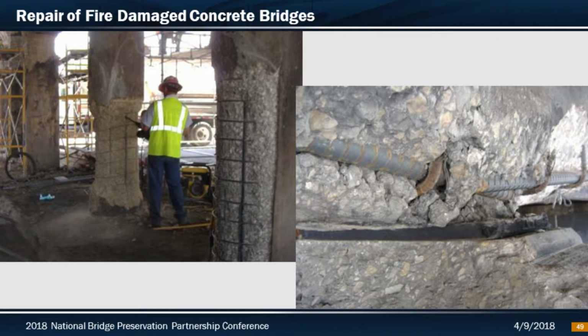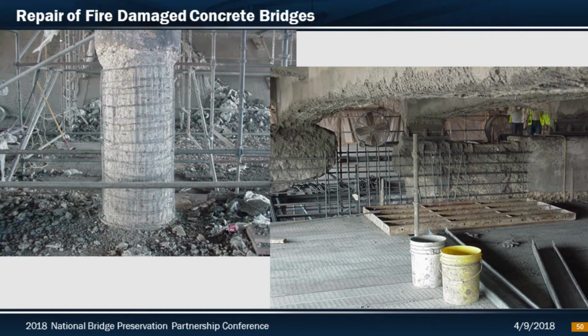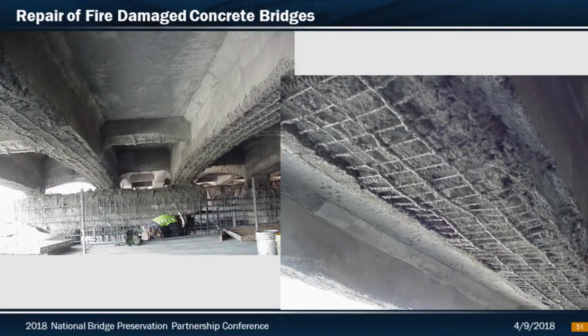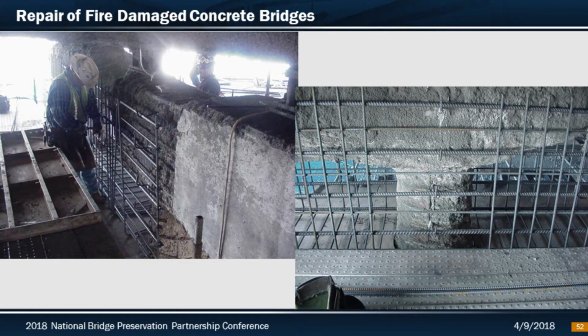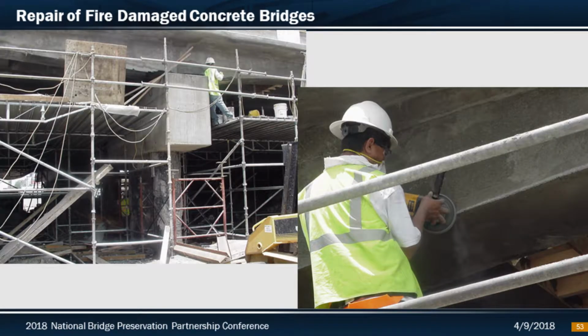Similar to our beam repairs, you chip out the unsound concrete and blast clean prior to your pneumatic concrete placement. Additional wire fabric was wrapped around the column to help engage that patch. On the right, you can see the reinforcing starting to go in for the bent cap encapsulation. It was cleaned off, sounded, cleaned, and then again just encapsulated in an additional bent cap with traditional concrete. Picture of the new reinforcing steel with the preliminary shotcrete system. Forms removed on that interior bent cap, a little oversized. In the right picture, again, you want to grind those edges smooth so you don't have any rough corners where that CFRP ends up wrapping around your beams.